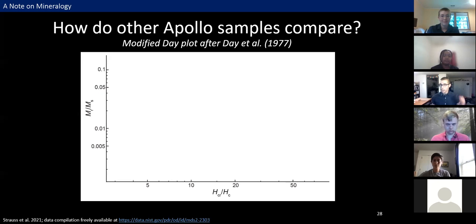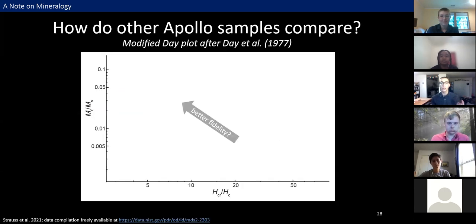So what I'm showing here is a Day plot, and these are typically used to understand how the hysteresis parameters of different samples relate to each other. On our x-axis, we have remanent coercivity divided by coercive force, and on our y-axis, we have saturation remanent magnetization divided by saturation magnetization. And the hope with a Day plot is that samples with better recording properties should plot toward the upper left, and that should correspond with better magnetic fidelity.